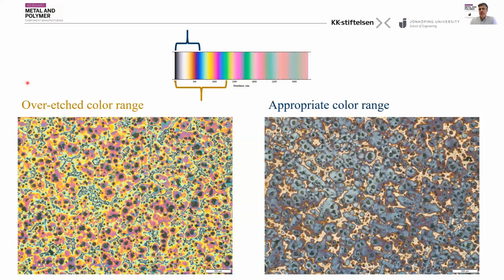Here we can see an example of the ductile iron microstructure of the over-etched sample on the left and the normal color-etched sample on the right. As you can see, the appropriately color-etched sample has a well-etched structure. You can see that the different microstructural features are much more distinguished. You can see very clearly where the austenite is, together with the graphite particles. We can see some dendrite arms alone, and we can also observe the dendritic phase very clearly.